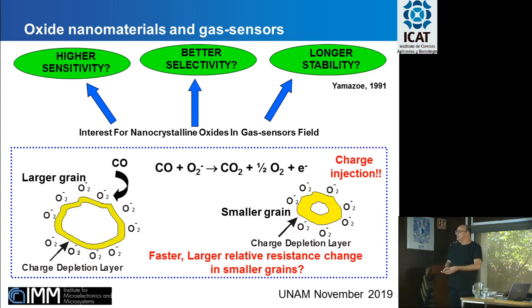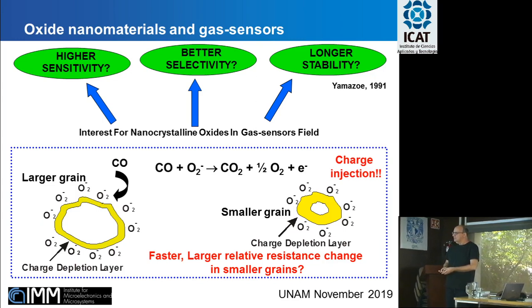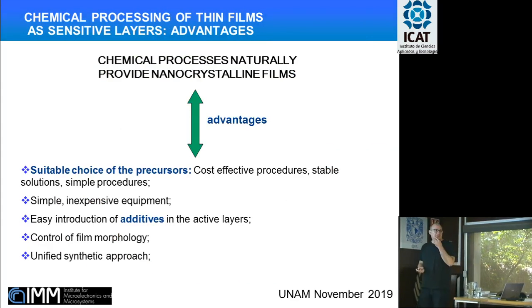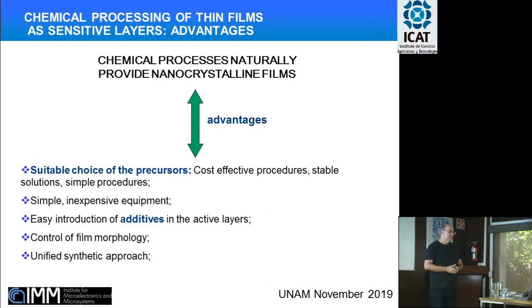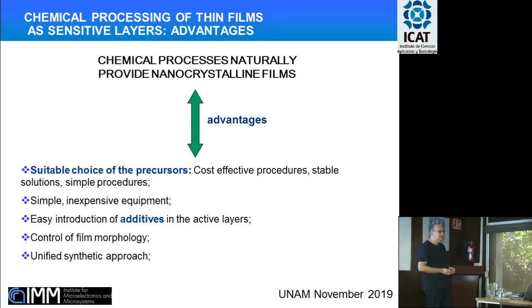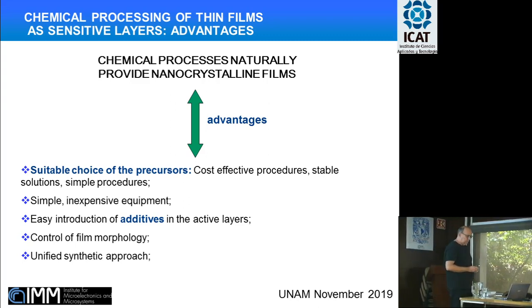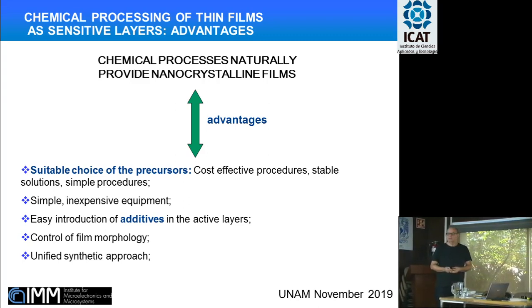Very, very briefly, we can think that we have a larger grain. The charged depletion layer which is formed upon interaction of the sensor with oxygen is less important with respect to the whole grain than in the case we have smaller grains, where the charged depletion layer is more important. So it is expected that we may have faster and larger relative resistance change in smaller grains. For this reason, an intensive research effort started since then, and still it is going on, for developing nanomaterials and for applying them to this kind of chemoresistive sensing devices.